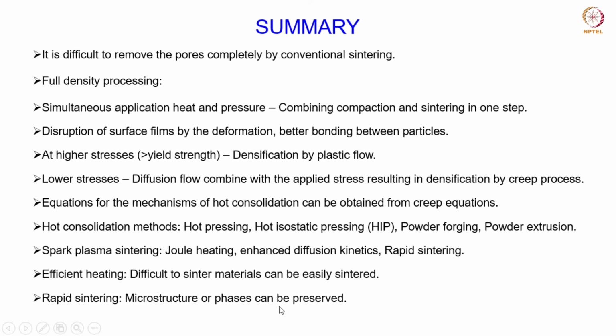Similarly, if a particular phase has to be preserved, that can also be done, since again, as I said, there is no time for any phase transformation to take place, right? So these are the different advantages which can be achieved with the help of this spark plasma sintering, because of its efficient heating and the enhanced diffusion kinetics which result from the uniform heating that occurs through the generation of sparks between the particles. All right, so that's all I have.